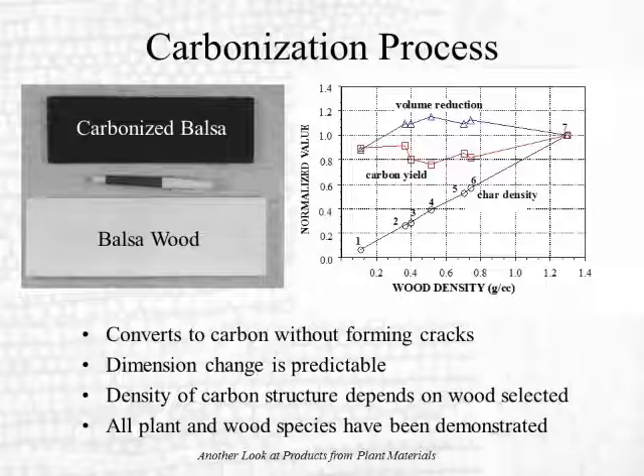Another visual on the upper left, where you take balsa wood, a stick of wood, you make it into charcoal, and you have volume and dimensional reduction. The graph here shows how you can select a variety of different woods from something very light like balsa wood with a low density up to something very dense like lignum vitae, which is high density, and several different wood species in between, all with different densities. And when you carbonize it, you get different carbon yields from each of them, and you get different volume reductions for each of those wood species.